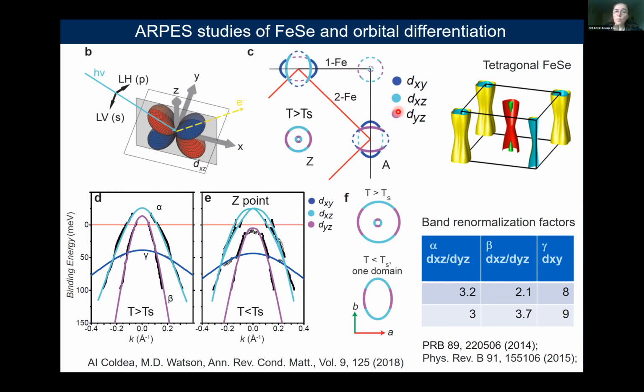And for the electron bands, we can expect also to have the dyz orbitals. Now, in experiments, despite the predicted Fermi surfaces of iron selenium to have 3 hole bands, in experiments at high temperature, we only recover 1 single cylinder and a very small 3-dimensional Fermi surface centered at the Z point.